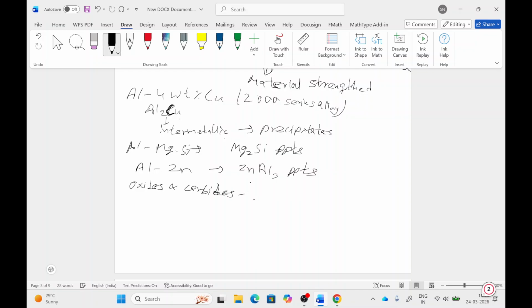carbides are called dispersoids. So dispersoids and precipitates also differ from each other. The dispersoids are like tungsten carbide, molybdenum carbide, vanadium carbide, and Al2O3. When these particles form, they are stable at high temperature, so they can still provide dispersion strengthening, meaning they maintain the strength of the material at high temperature.